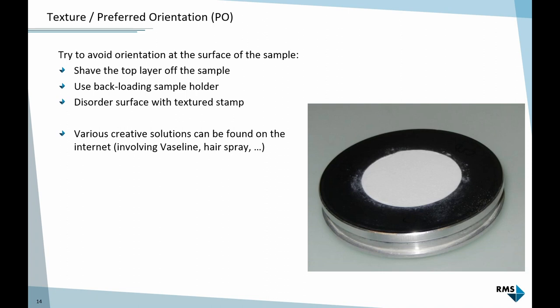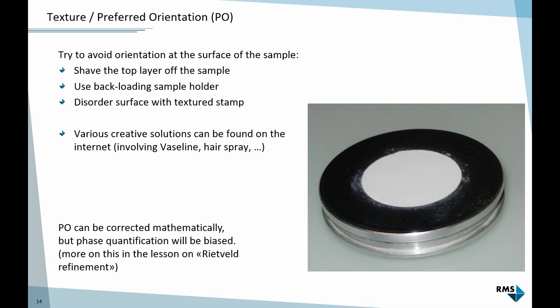Or you can texture the surface with a pattern, with a dented stamp pressed into the surface to create roughness. If you search on the internet you'll find rather creative solutions, some involving Vaseline - you create a sticky surface, sprinkle powder on it and crystals fall and stick in random orientation. Or fix the surface layer with hairspray in a disoriented way.